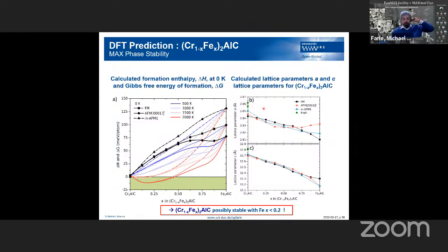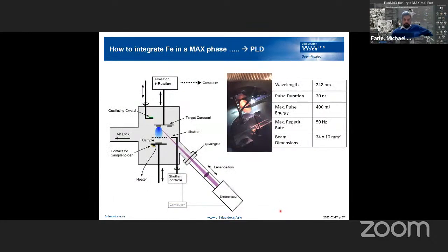So with Martin and Johanna, we have a nice competition or friendly discussion if theory or experiment is incomplete. So that's very nice to see that we need theory to understand what's going on and to guide us which materials to mix. And according to theory, it should be possible to go up to x of 0.2, but this doesn't work. So Ulf tried that and Hanna Pasniak, they tried it, but it works with pulsed laser deposition. It works only, what was it? I think 0.4% of iron.